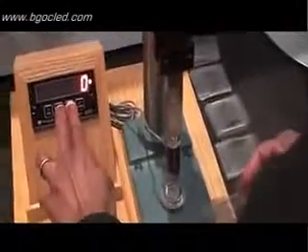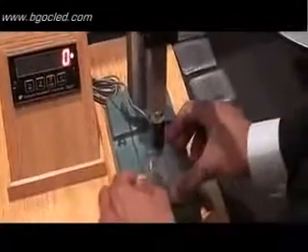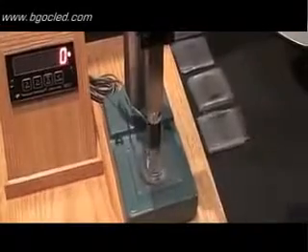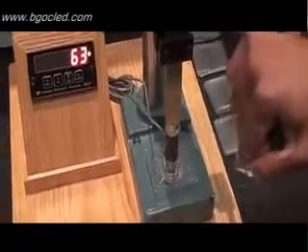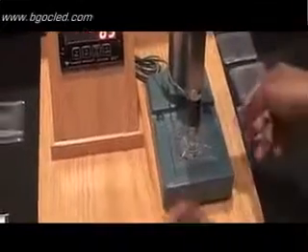Here's a piece of strengthened soda-lime glass — just the same glass, 1.1 millimeter thick, but it's been ion exchange, so it's been strengthened. 63 pounds. Not a whole lot more.